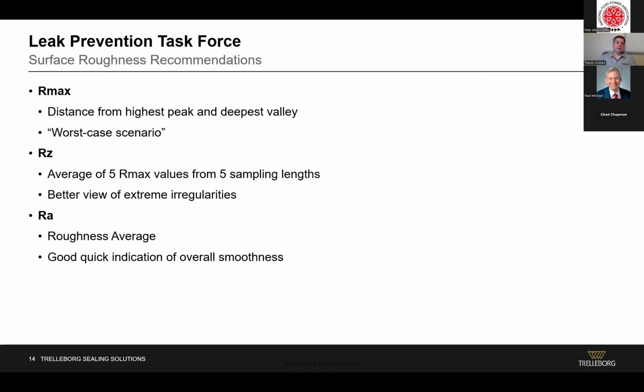So Rmax is one. Rmax is the distance from the highest peak to the deepest valley on a surface finish. It gives you a worst case scenario, what you're up against. If there's some major defect on the surface, it will tell you that. Rz is an average of 5 Rmax values from 5 sampling lengths. So you look at 5 sampling lengths, take the worst case scenario from each of the 5, and then average them out. That gives you a better view of the extreme irregularities on the surface. Not just the worst case scenario, but a little bit better picture.